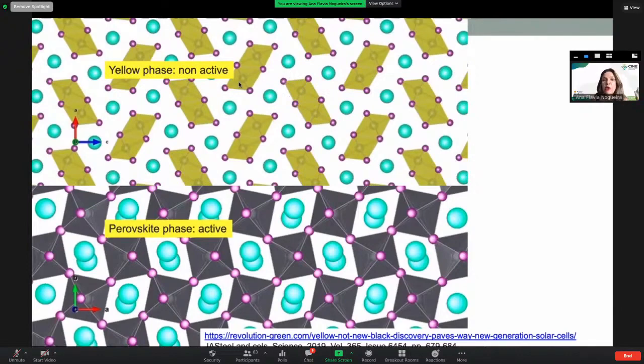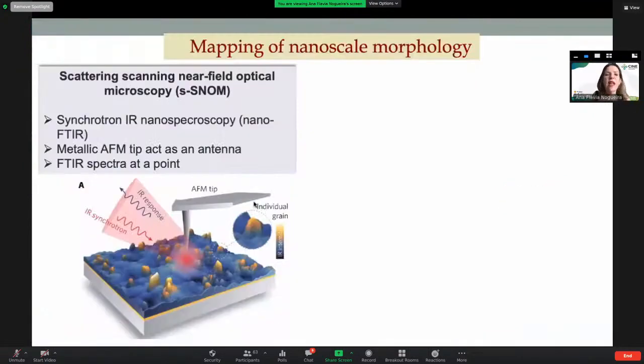So I don't want this yellow phase, but the question that we asked some years ago was: can you see where these yellow phases are in the film? So we went to the synchrotron, now not only to use the X-rays, but also the infrared. This technique is going to be available again by the end of this year. It is called nano infrared, nano FTIR.